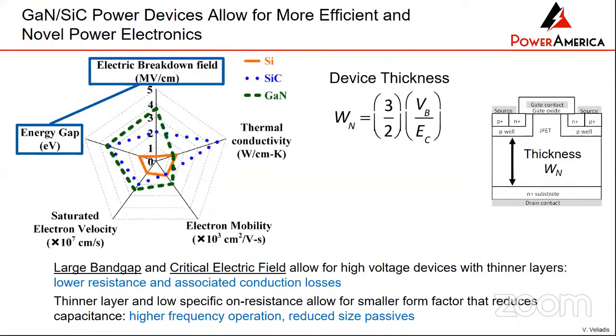And you can see from this equation that the thickness of the device is inversely proportional to the electric breakdown field, the critical field, okay? This property right here. So if you make a device out of silicon carbide instead of silicon, because silicon carbide has 9 times higher breakdown field, then the device will become 9 times thinner. And if you look at the resistance,